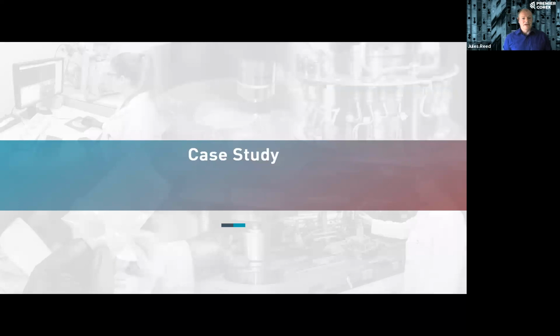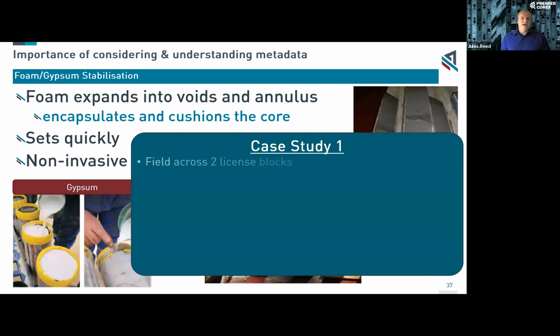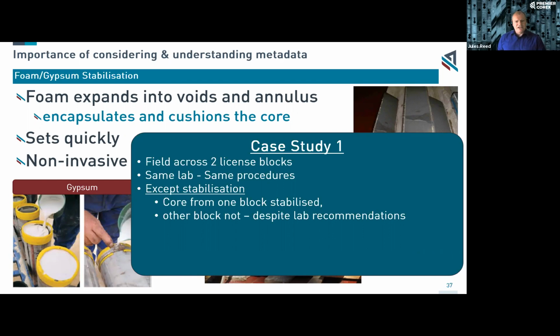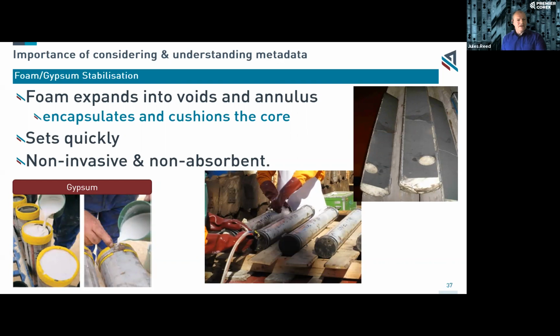One of them is a case study where we had a field across two license blocks. In each license block, there were two operators, but there was a partner who saw across both license blocks. And they saw different properties, but it was the same lab, and the lab was using exactly the same procedures, except stabilization. By stabilization, I mean this process here that I'm showing on this slide. At the well site, as the core comes to surface, the core is stabilized.